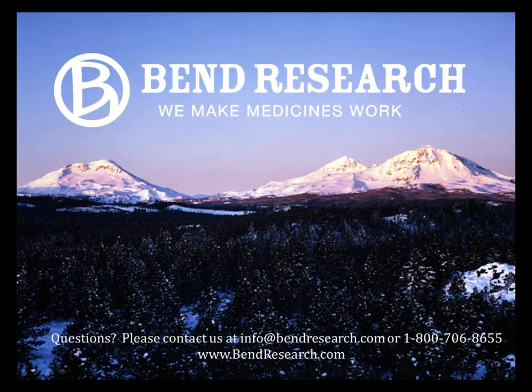No, that's a good question. Yeah, I think from the standpoint of proteins, it's an important hypothesis around why people use sugars. We try to combine that theory along with the high Tg theory, looking at polymers in matrix, amorphous matrices, that actually stabilizes that. And so we push a high Tg formulation approach over the hydrogen bonding approach. We do use those hand in hand to understand how a formulation will stabilize a biotherapeutic. As I mentioned earlier, there are a few different theories out there around hydrogen bonding and excipients and protein stabilization. So we try to combine that mode of thinking along with the classic amorphous dispersion high Tg approach for small molecule formulation as well. So essentially it can be like a blend of thermodynamic stability versus kinetic stability. Exactly. Thanks, Devin.